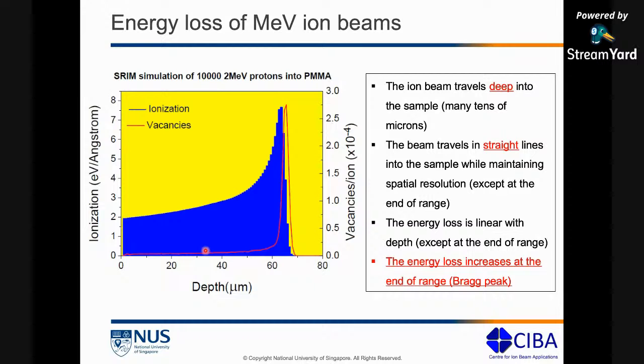So you have these two distinct effects that come with high energy protons entering into a material. You have the streamlined entry effect with minimum scattering, and then you have this huge peak at the very end where they come to a complete stop and deposit all of their energy. These two effects add up to give a huge advantage of using protons for proton beam therapy, and this is something I will explain in my last slide. These are exactly the two distinct advantages of why high energy protons become very useful when it comes to proton beam therapy. And we cannot use electrons for this. Electrons will not give you this effect. That's a distinct advantage of using protons over electrons.